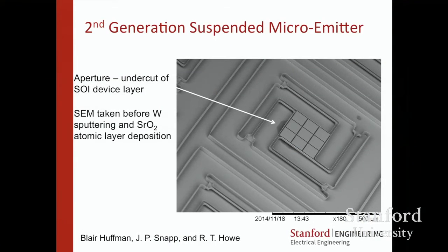So what it actually looks like is kind of cool if you're into 3D micromachining. There's a hole underneath that wasn't quite perfectly aligned, you can kind of see, and we have this grid structure where we would put the tungsten and then surface coatings of like barium, strontium to lower the work function further. And we would deposit those coatings using atomic layer deposition, not the kind of old school mortar and pestle technique. So you would have something that you could crank out huge amounts of.